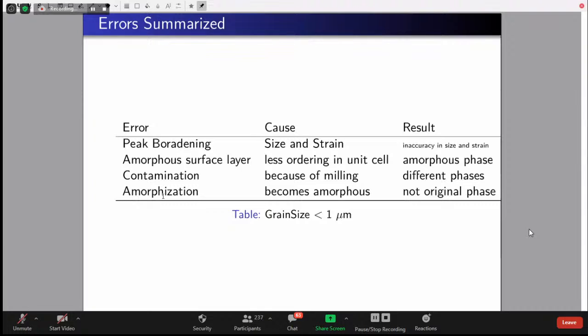Next one is if you overgrind it. Below 1 micron, if you overgrind it, all the peaks will broaden, certain amorphous content will come in, and contamination will come into the picture. This contamination will not come if you are using mortar and pestle, but in some labs, people use a tiny ball mill where they overdo this milling. When we overdo this milling, certain amount of the material of the balls used for milling will come into ours, and then we will have contamination.